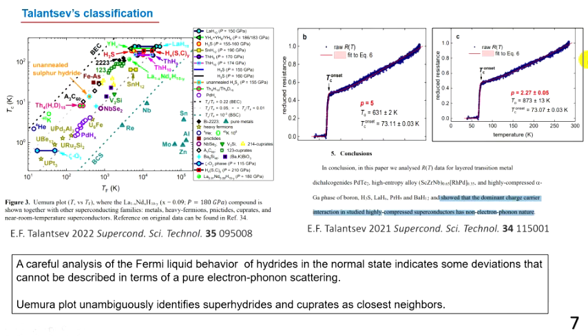And here I would like to say a couple of words about Eugen Talantsev's publications. He published several papers in 2020-2022 and analyzed Uemura plot. He always underlined the fact that all compressed polyhydrides belong to an unconventional region in this plot. And this plot unambiguously identifies superhydrides and cuprates as the closest neighbors. Moreover, in 2021, Talantsev showed that careful analysis of the Fermi-liquid behavior of hydrides in normal state indicates some deviations that cannot be described in terms of pure electron phonon scattering.